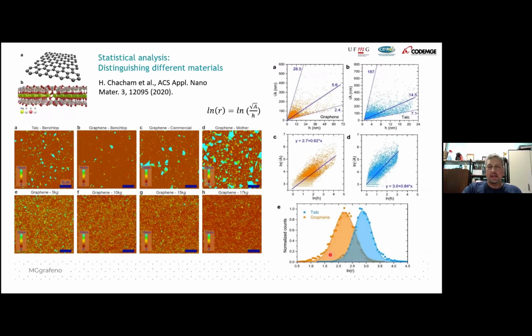All right, so with these statistics in hand, we have different approaches that we can make, but this is just one showing here that we can make all these charts. For example, the square root of area as a function of the height. We measure different materials as an example. For example, this is talc, and this is graphene, and this number is quite interesting, the aspect ratio between the average lateral size and the height. This is what we call the R ratio. And we show that different materials give you different statistics. This is based on between 10,000 and 15,000 flakes.